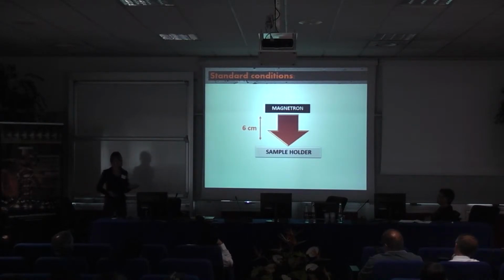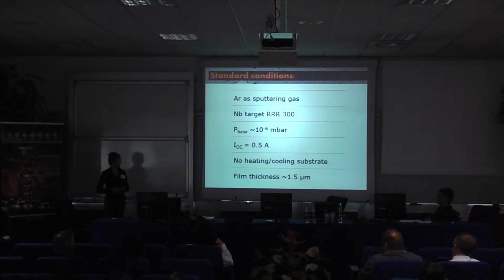The standard configuration that we have used is magnetron up and sample downside. The distance between magnetron and sample holder has been kept standard. Argon has been used as sputtering gas. Niobium targets of high quality, RRR of 300, have been used. The base pressure was of the order of 10 to minus 6 millibar, DC current 0.5 amperes. In standard conditions, we have not used heating or cooling of the substrate, and the film thickness was around 1.5 micron.